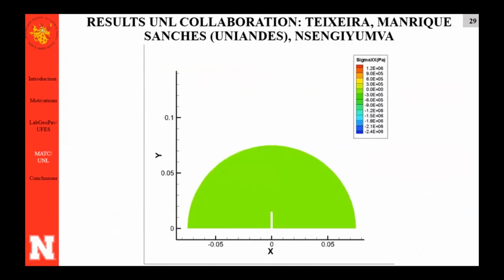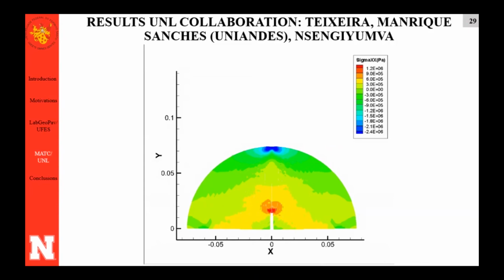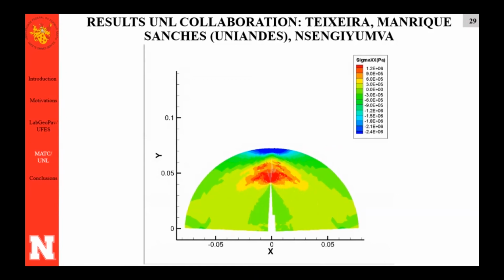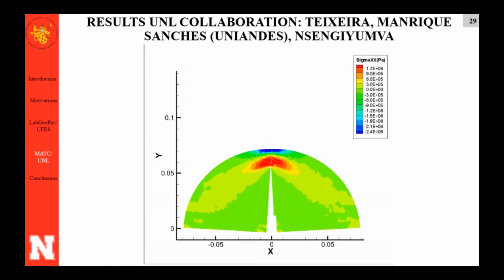So here is a movie. So you can see we apply the load here at the center middle point. So we have tensile stress concentration here close to the notch tip, and compressive stress concentration here where the load is applied. And after a certain level of tensile stress, we have cracks start to be developed and being propagated throughout the sample. So that's what we predicted numerically. And the same behavior that we obtained numerically was also observed in the experiment.